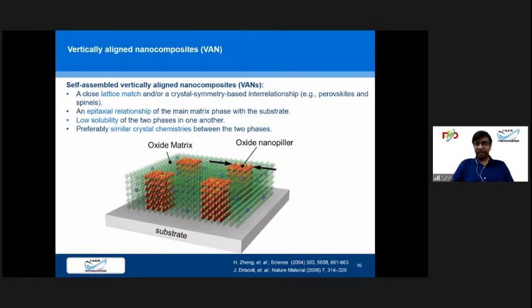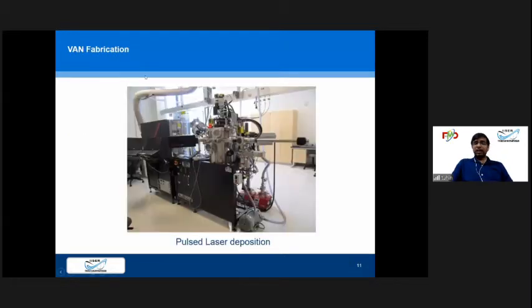My group in Cambridge has worked on this for 10 years. And in the last 2-3 years, we have started getting very nice results out of this kind of structure in different materials. So I'll discuss that. In Cambridge, we used pulsed laser deposition to prepare these samples. If someone is not aware of pulsed laser deposition, I will just briefly explain. There is a high energy laser, this box, which can create a very high energy laser pulse, like 500 millijoules. And this is the vacuum chamber, and there is a target and the substrate.